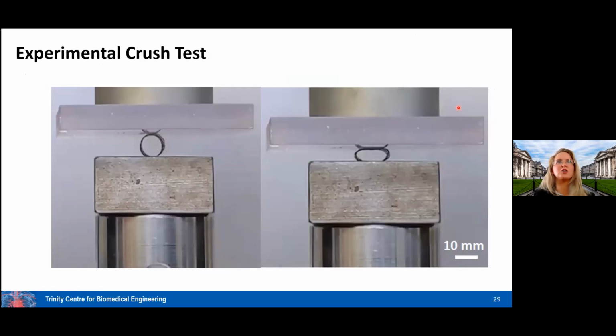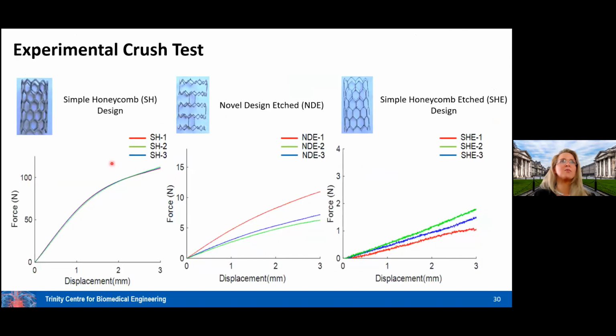But here's just an image now showing you those stents being crushed using a parallel plate testing setup where the force that's being applied to the stent is measured as the stent is deformed here. And doing this, we can get out from that what is the radial stiffness, what's the force needed to crush those stents. So here, the simple honeycomb, the thickest strut stent, as you can imagine, this one is going to have a greater radial stiffness. In fact, it takes around 100 newtons to compress that stent to 3 millimeters. Whereas when we look at the novel design etched with those thinner, around 200 micron struts, we see that it takes about between 5 and 10 newtons for each individual stent.